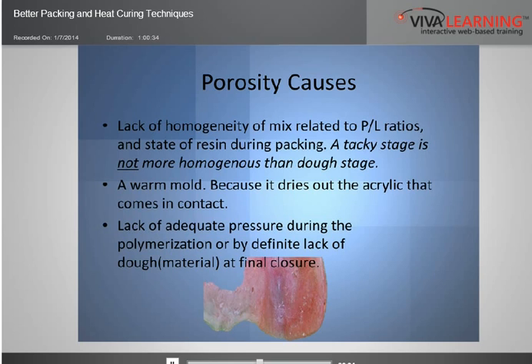And here's one. Lack of adequate pressure during polymerization. In other words, your flask compress is not the same as it was when you first bought it, and maybe those springs are a little loose, or maybe you didn't turn it and tighten it enough, or maybe you didn't have enough dough in your flask, maybe because you're one of those guys that likes to throw a ball in there and close it, and sometimes you get some that squeezes out the edges, and sometimes you don't. If there's not enough pressure inside the mold, and I know that I've done it myself, if you underpack a case, you and I both know that it comes out porous. Well, if it's underpacked dramatically, we notice it. But if there's not adequate pressure and it's not noticeable that we haven't at least flashed the material a little bit, we'll still have the chance of getting that porosity.